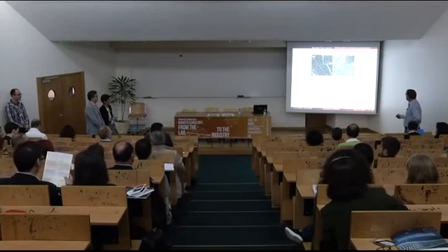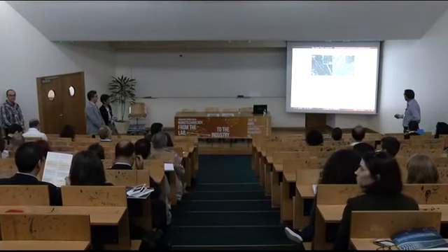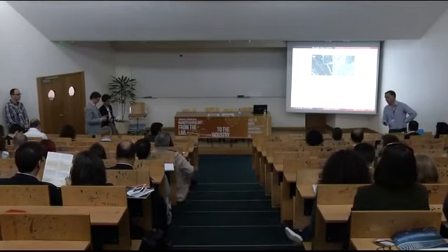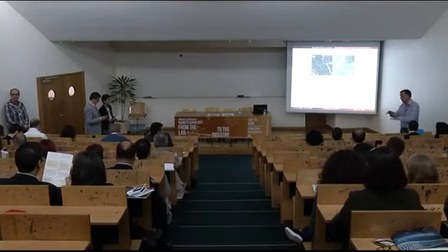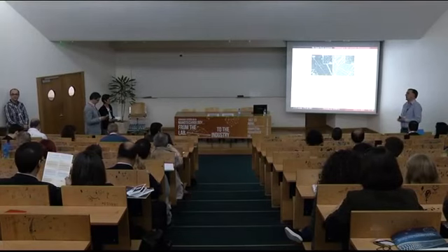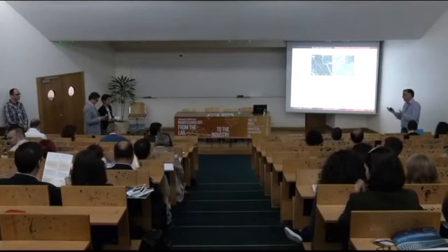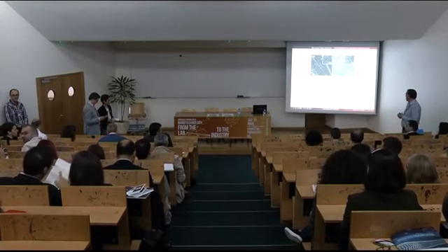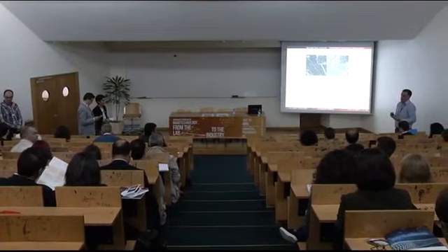You can see in both images that the epilayer underneath the nanowires is not a flat epilayer. So we have two problems. We have not a flat epilayer on one side, and on the other side we have the lattice mismatch.